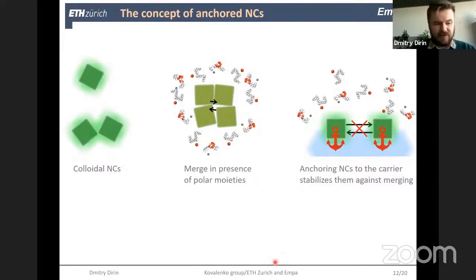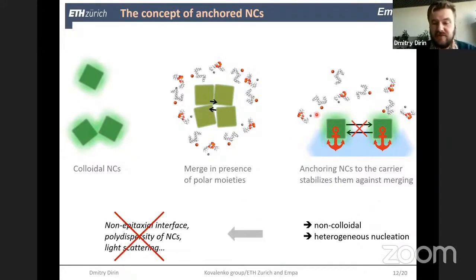If you're from the field of colloidal nanoparticles, you can immediately say that there are several issues. First of all, in this case we don't have burst, homogeneous nucleation. We will have to work with heterogeneous nucleation, and usually for colloidal nanoparticles that is a big problem because you will have very polydisperse nanoparticles, and then you have a very broad luminescence peak. But in the case of perovskites, it turns out to be, again, not critical, because we are now working in a weak confinement regime, and even a broad size distribution will not induce a broad photoluminescence peak.